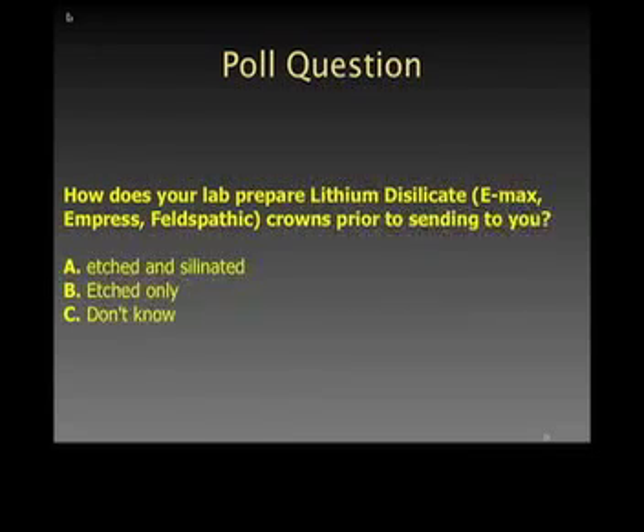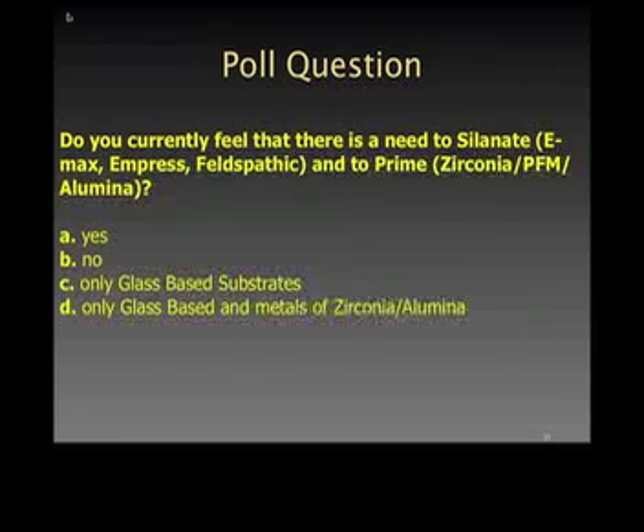When we talk about feldspathic and lithium disilicates, they're silica-containing glass oxide with an amorphous glass phase. So proper mechanical bonding, including sandblasting and hydrofluoric etching, leads to immediate bond strengths. However, proper chemical silane application will lead to long-term durability. So we not only want strong bond strengths, but we want them to be durable too. That's an important part.